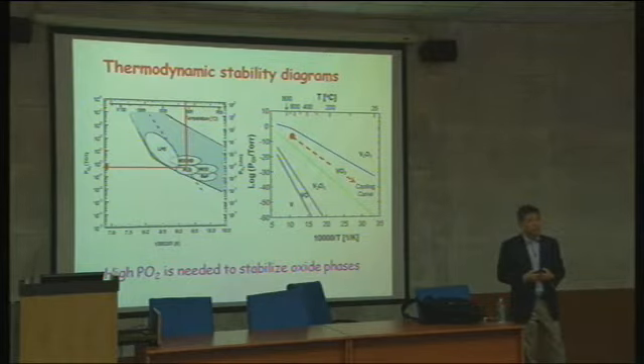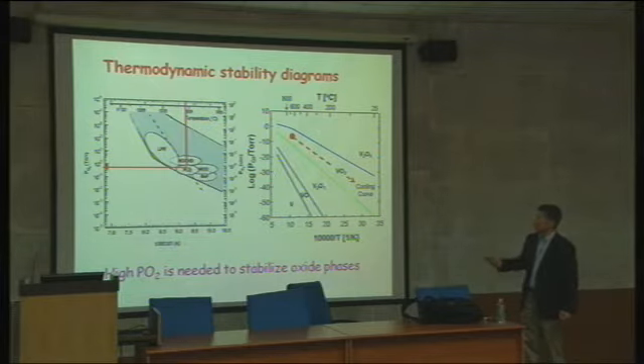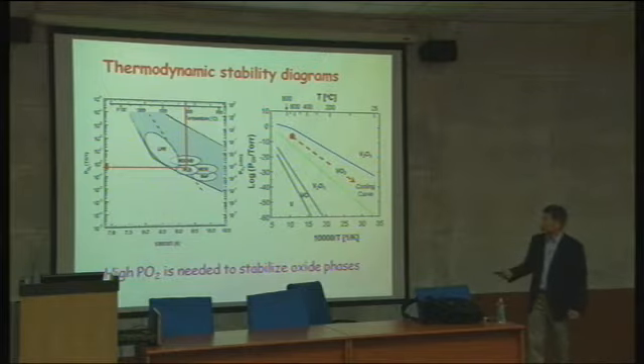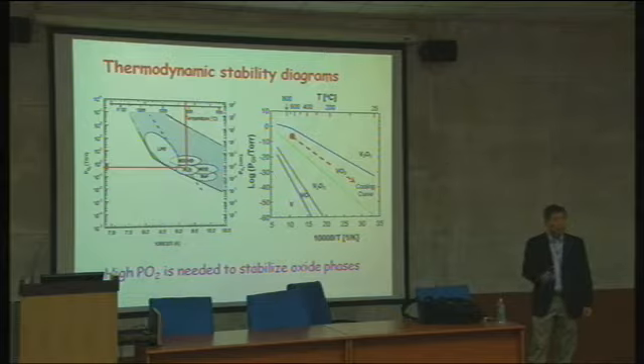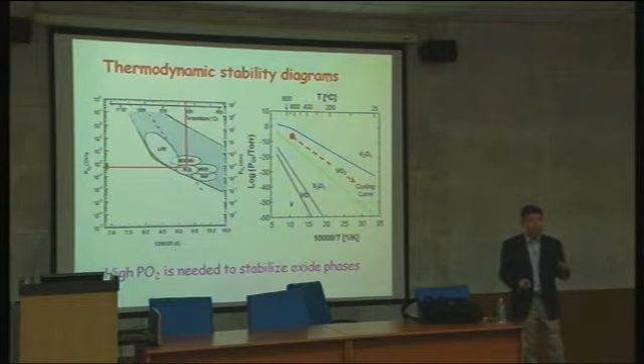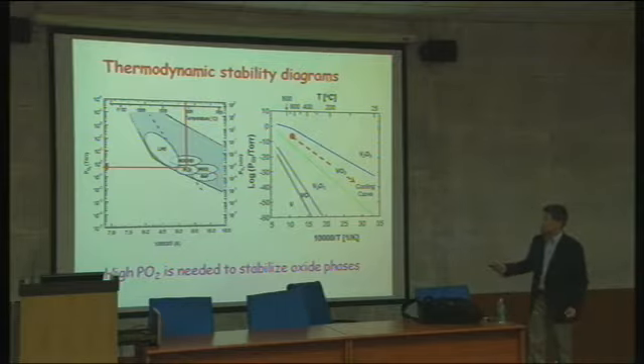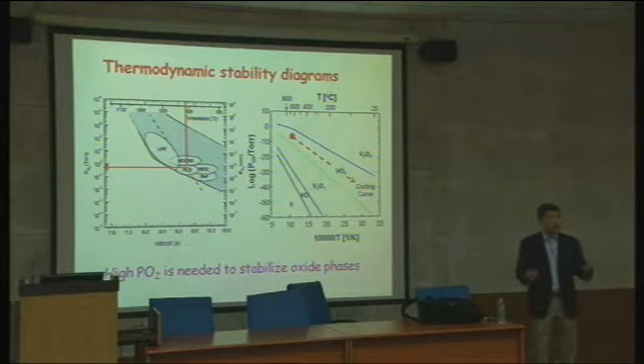How much oxygen do you need? How much oxygen you need to stabilize a certain type of material depends on what material you grow. Some materials need tons of oxygen, some need very little oxygen, depending on the stability of your materials. For example, in yttrium barium copper oxide, this phase diagram people actually studied shows oxygen partial pressure and temperature, and depending on temperature and oxygen partial pressure, this is the region where you can stabilize the yttrium barium copper oxide superconducting phase. Below this region, with oxygen partial pressure lower than this, it will decompose to a different compound, which you don't want. So you need a minimum oxygen partial pressure above this region, which is relatively very high.